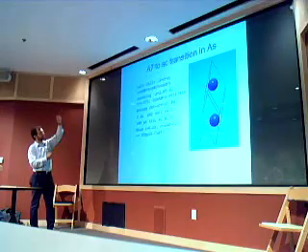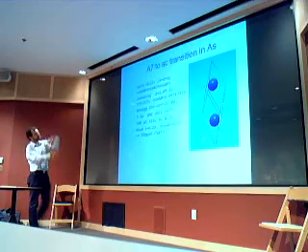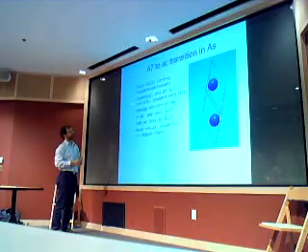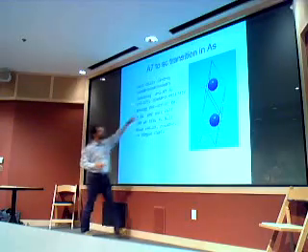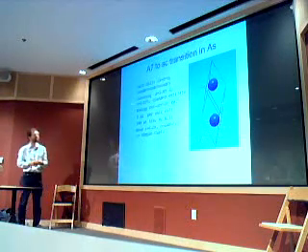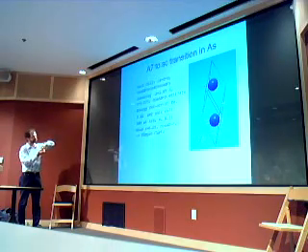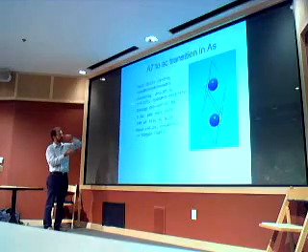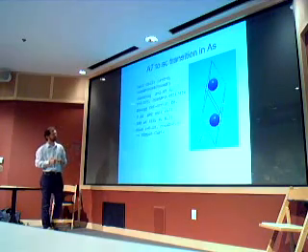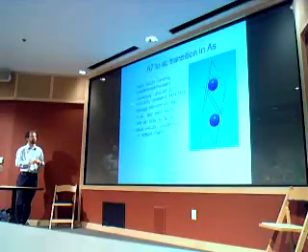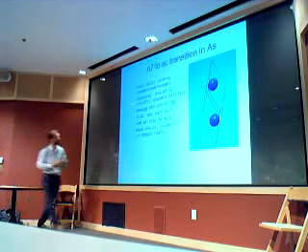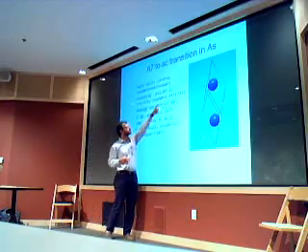So when you squeeze the simple cubic along the 111 direction, so that the cosine between two vectors becomes less than 60 degrees, then the arsenic will show this structure at zero pressure, and instead above a certain pressure, which is of the order of 20 or 30 GPa, so 300, 400 kilobar, it will go back to the cubic system, to the cubic cell, in which this angle is 60 degrees.